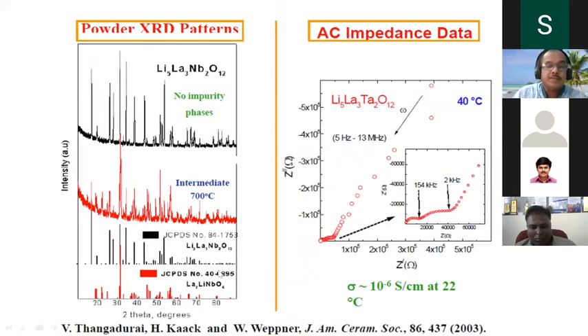So, able to synthesize at 700 and no impurity phases, very good, able to reproduce. They then started to, because being electrochemists, our group is interested in the conductivity. So this is the impedance pattern of this Li5La3Ta2O12. They realized the conductivity is something around 10 power minus 6 siemens per centimeter. So our target is 10 power minus 3 at ambient conditions. So at least 3 orders of magnitude higher.